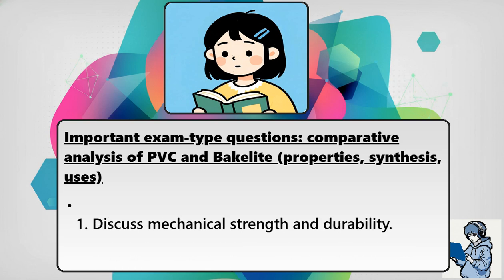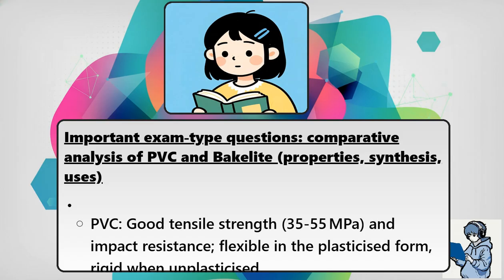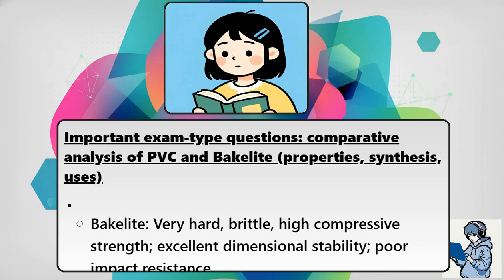1. Discuss mechanical strength and durability. PVC: good tensile strength, 35 to 55 megapascals, and impact resistance. Flexible in the plasticized form, rigid when unplasticized. Bakelite: very hard, brittle, high compressive strength, excellent dimensional stability, poor impact resistance.